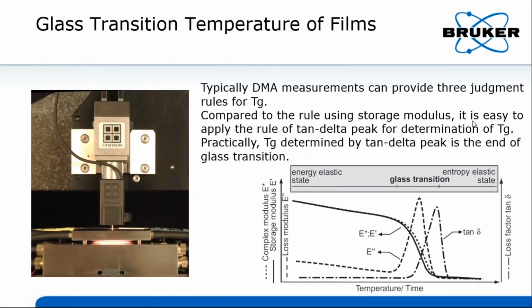Talking about the glass transition, dynamic mechanical analysis (DMA) is one of the commonly used techniques. DMA measurements can provide three judgment rules for glass transition temperature, Tg for short. One is storage modulus onset, and the other two are loss modulus peak and the tan delta peak. Compared to the rule using storage modulus onset, it is easy to apply the rules of peaks for determination of